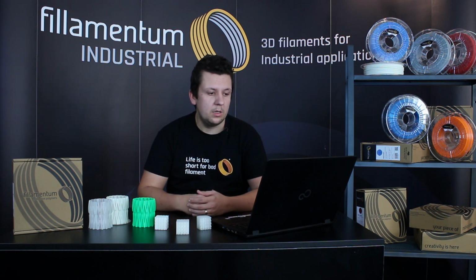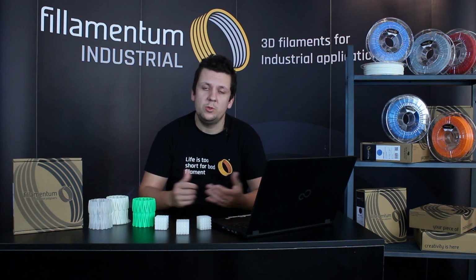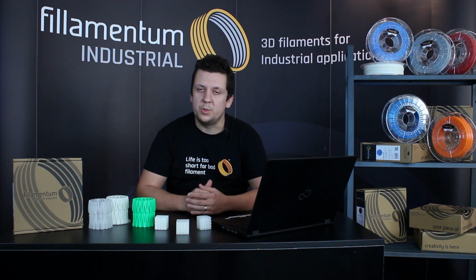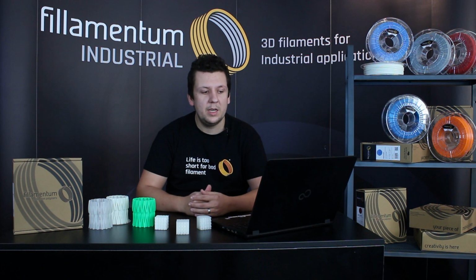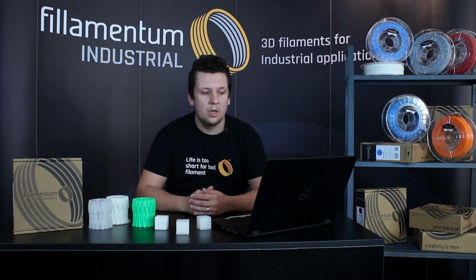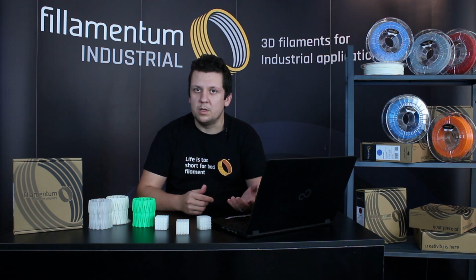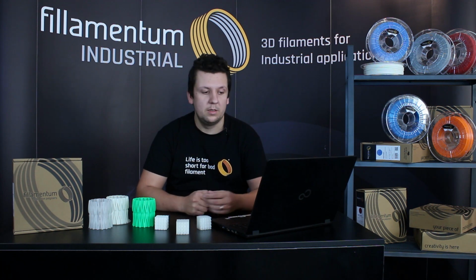And what is really necessary to mention, if you have a printer with a Bowden setup, it can be quite tricky to print with flexible materials with an unmodified extruder because of the play in the tube. The 98 Shore A is definitely printable on Bowden setups with no modifications from our experience. And if you have the softer ones, maybe you have to switch to a direct drive extruder, which is better for printing, or you have to modify the extruder to be able to print it.